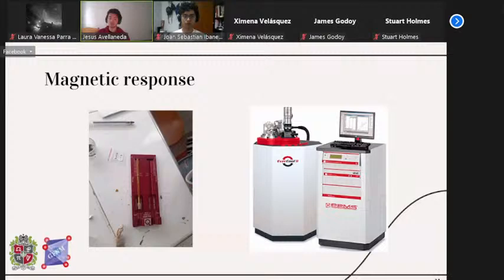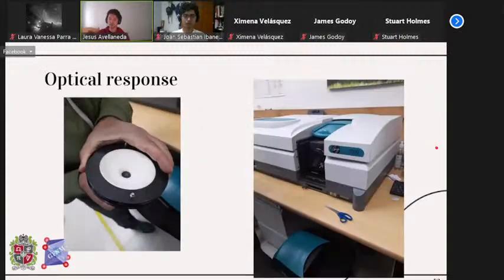Also, for the magnetic measurements, the UPTC, through Ms. Milena Saavedra and through Professor Carlos Parra, if I'm not mistaken, allowed us to use a VSM to perform the magnetic response measurements. And finally, for the optical response, in this case, it was a plus for the work because we had problems with the electrical response machine. The day that we were supposed to take said measurements, the machine broke. So we thought at that time that we were able to obtain relevant data through an optical response analysis.